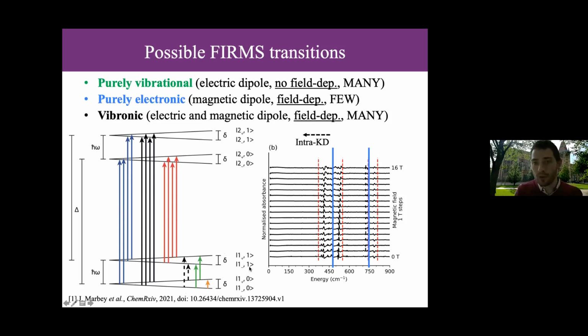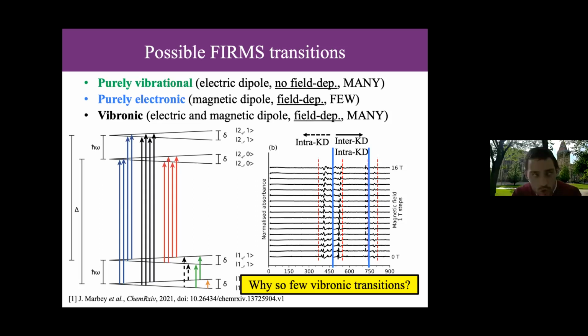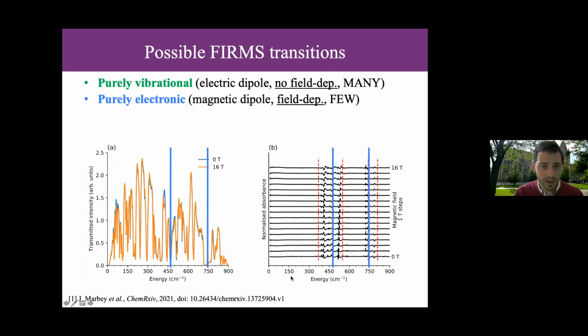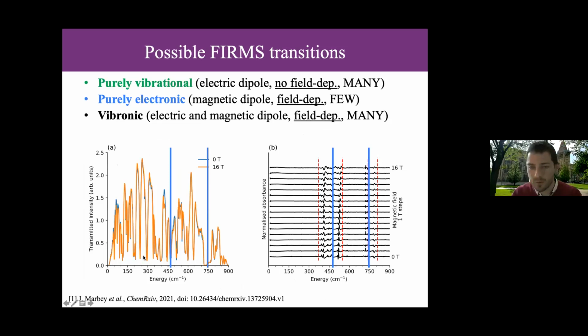So on the left of those, we must have intra Kramer's doublet. On the right, of course, we could have inter Kramer's doublet, intra Kramer's doublet, and any kind of thing. Okay, but on the left, we must have intra. And so the question really becomes, if we can have intra Kramer's doublet transitions, that is a tiny EPR electronic transition, but then any vibrational mode on top of that, why aren't we seeing vibronic intra Kramer's doublet transitions all over this region? 150 wave numbers. If you go back to the raw spectrum, we have a heck of a lot of vibrational modes in this region. Why are they not observed in this spectrum?